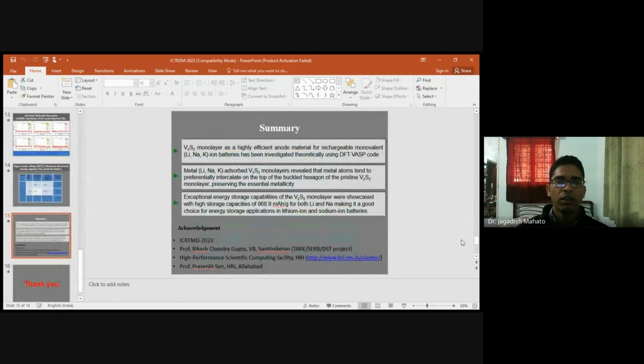So in summary, V2S2 monolayer as a highly efficient anode material for rechargeable monovalent ion batteries has been investigated theoretically using the DFT VASP code. Metal atom adsorbed V2S2 monolayer reveals that the metal atoms tend to preferentially intercalate on top of the buckled hexagon of the pristine V2S2 monolayer, preserving its essential metallicity. And exceptional energy storage capacities of V2S2 monolayer were showcased, with a high storage capacity of 966.9 milliampere hour per gram for both lithium and sodium, making it a good choice for energy storage application in lithium-ion and sodium-ion batteries.